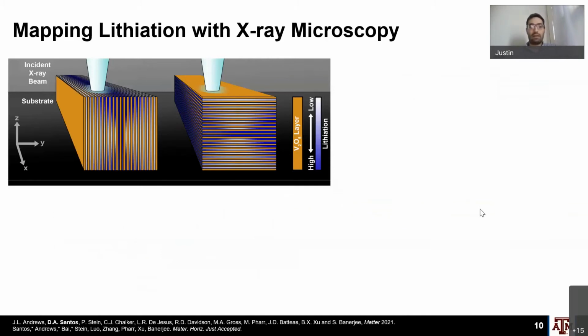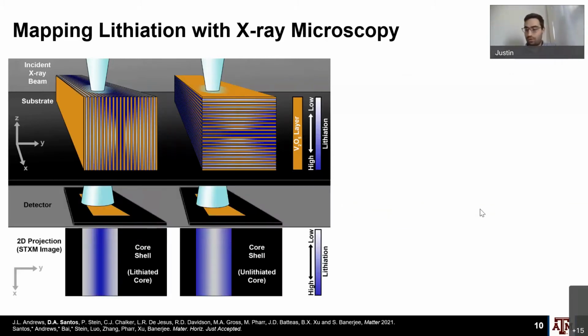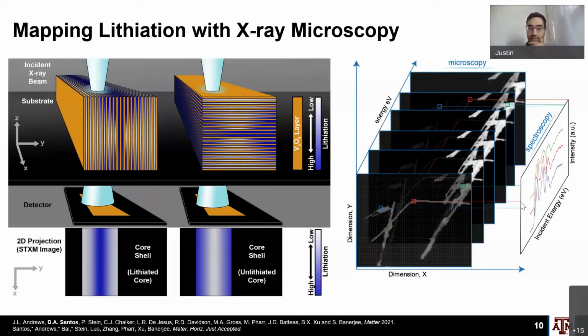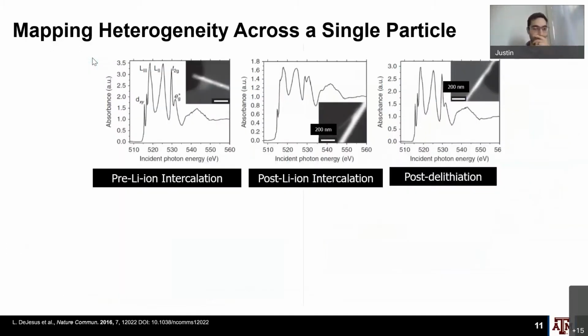And so I'm going to be talking a lot about X-ray microscopy, and I'm sure the majority of the audience is familiar with how this works, but we have these, typically in our case, nanowires, and we can have different orientations of these nanowires, but essentially we're taking 2D images of these. I think this graphic shows it simply: we have an image, and we actually more or less have a movie, and so at each energy that we scan across, we take an image and we compile these, and so at each pixel we have a spectrum that is contained within that pixel that corresponds spatially to that location, and then we can look at how these features evolve spatially.